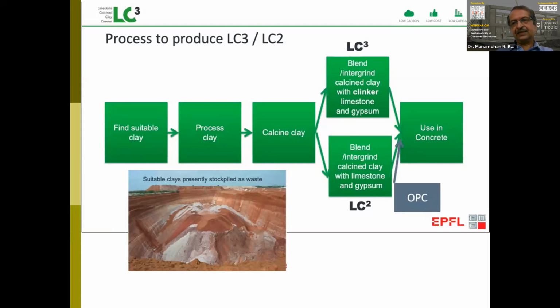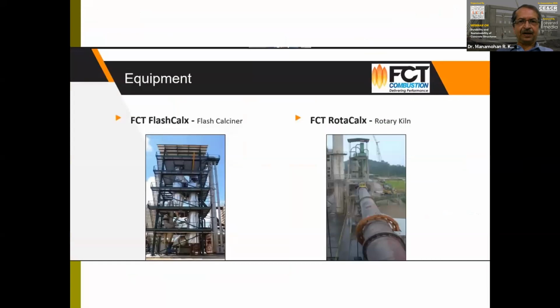So here the greatest attraction is that the clay, which has very low kaolinite content of maybe, let's say, 40 or 45%, which is not suitable for other industries like ceramic, paper, etc., which is now lying stockpiled in various places, can be fruitfully used. So the calcined clay that you use is of much inferior quality, and plenty of such clays are available across the country in most places. So this is another application that people are now going to look at, because BIS also has come out with the draft code, and once it becomes approved, then you can legally use this.